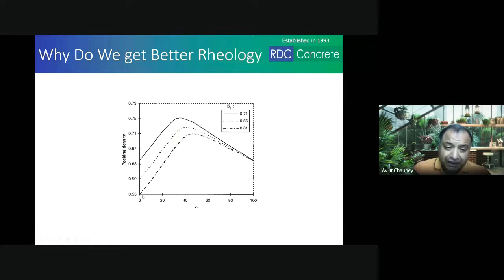So lesser particle packing means the aggregate is flaky. Higher particle packing means the aggregate is less flaky, and the highest particle packing is not flaky at all. It is either spherical or cubical in shape, a good shape. So when you are mixing a flaky aggregate and a normal, good aggregate, the flaky aggregate, even at the highest packing density, will be much less than the mixture of aggregates with good particle packing.